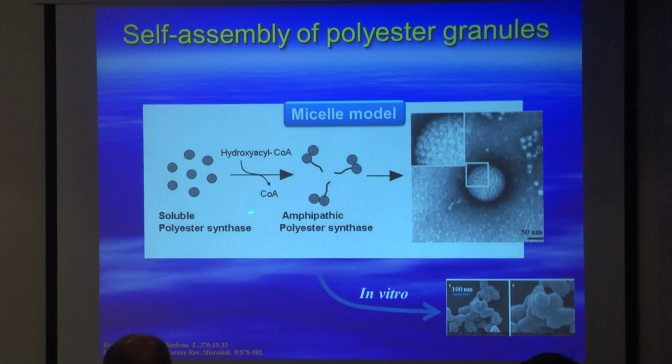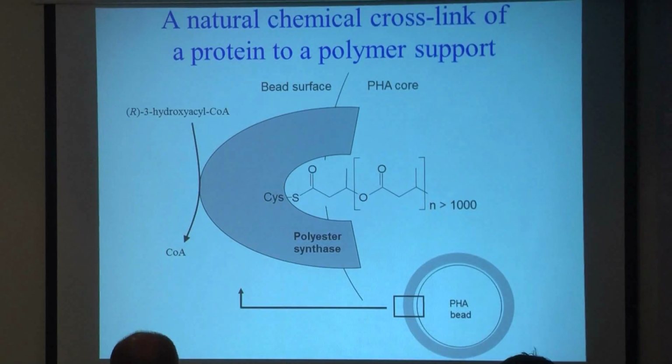You can also just isolate the enzyme and buy a substrate from Sigma, which is a racemic mixture, so you get only 50% utilized because it's a stereoselective conversion. And then you can make these granules in vitro, no problem. It happens quickly. You start with a clear solution, over time it becomes turbid, and you get those particles. The bacterial cell does this 4 magnitudes cheaper from glucose than buying that from Sigma as a pure chemical. And that's the advantage of the cell factory being utilized in that process.